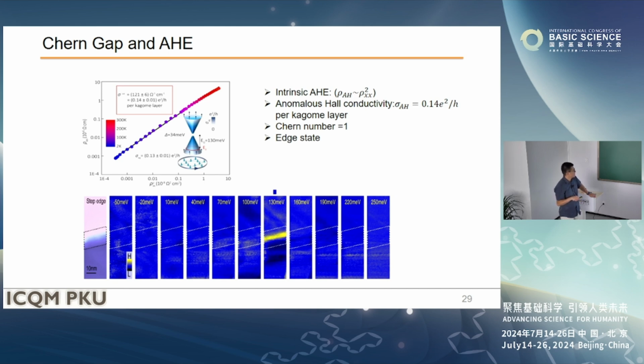Another measurement is the collaborator using STM with voltage. We see that when the voltage is around 130 meV, we see a clear edge state. So it's another consistency with the existing Chern gap because it has a topologically protected edge state.